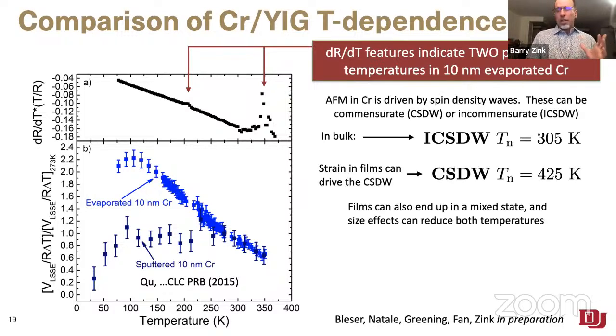So first, the antiferromagnetic state in chromium is driven by spin density waves. So what we've got is variations in the spin polarization of the Fermi surface itself. That Fermi surface and the variations on it, those spin density waves, can be either what's called commensurate with the lattice or incommensurate with the lattice. So that means that they're happening on different spatial scales, right? The bulk transition temperature we talk about in chromium, a 305 Kelvin or 300 Kelvin transition temperature for antiferromagnetic chromium, is an incommensurate spin density wave antiferromagnetic transition.